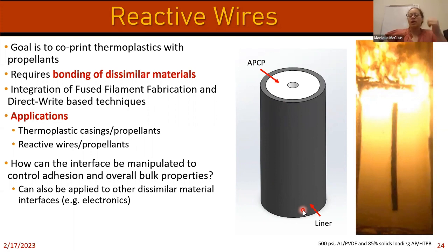So that's one application. Another application is from a combustion standpoint. We have the ability to make what are called reactive wires at Purdue. Essentially we can make a filament that can burn pretty fast. Those filaments can be made out of aluminum and PVDF, for example, and we have several papers on this at Purdue on how that is done. We've seen in the past that this can burn faster than the propellant around it. So the idea is that instead of trying to cast the central port so that we can control how the propellant burns over time, what if we filled the central area with just this reactive wire or some other interesting structure, so that when we burn it, it can open up this burning surface area very quickly.